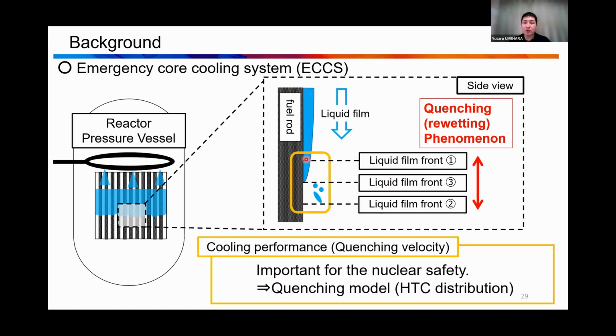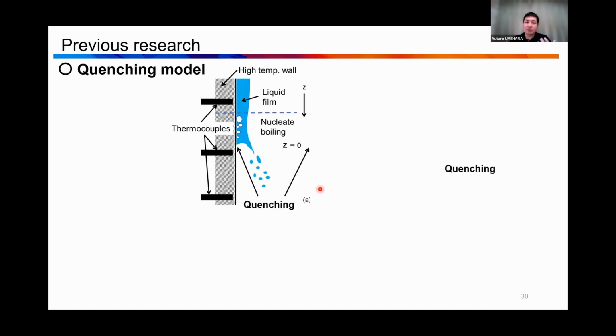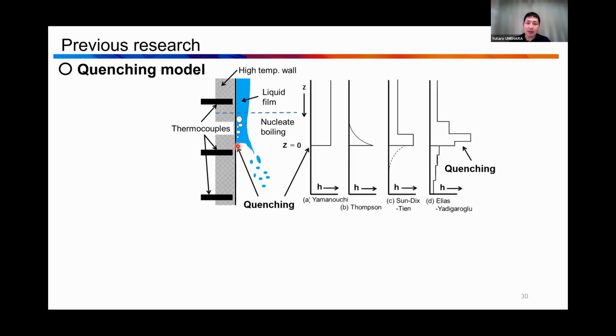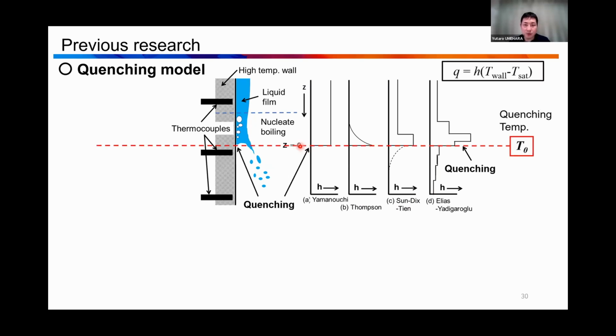So to predict the quenching velocity, we need to make some quenching model. The quenching model is an HTC distribution near the liquid film front here. Previous research reported various quenching models and then suggested a new quenching model. This one is a liquid film, and here is the liquid film front. This one is a quenching point, and they reported a kind of heat transfer coefficient distribution like this. And here is a constant heat transfer coefficient, but suddenly zero after the quenching temperature. But the other one slightly changes the heat transfer coefficient distribution.